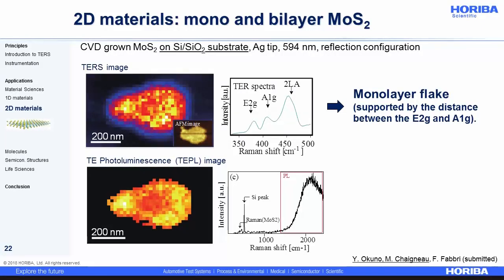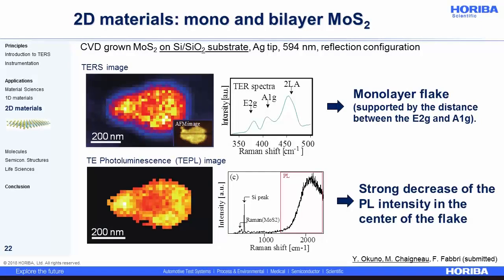photoluminescence is enhanced. As you can see here, the tip-enhanced photoluminescence map of the same molybdenum disulfide flake taken simultaneously with the TERS map. It is worth noting that in this nano-PL map, a strong decrease of the PL intensity is observed in the center of the flake. Also reported to some extent in the TERS map above.